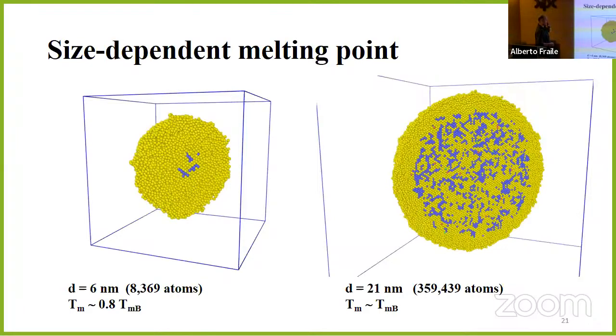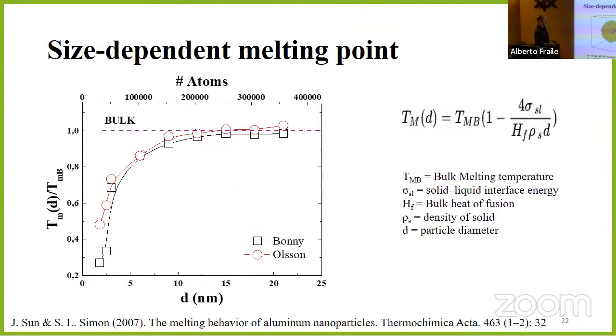And it has to be said also that when you are doing something very small, in this case, nanometers, there are things that are size dependent. For example, the melting point of these nanoparticles. In a nanoparticle this big, the melting point is 0.8 of the melting point of the bulk. In a nanoparticle like this, big enough, the melting point is almost the melting point of the bulk material. So this is also something to consider when comparing these results.